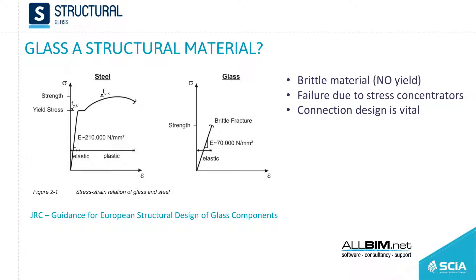Glass is quite a daring structural material because of its lack of redundancy. Glass is an elastic material, and when we compare it with steel or timber, those materials have the possibility of yielding. We can have plastic deformations and redistribution of tension, so if we under-evaluate the loads, distribution in plastic domains can ensure some redundancy to the structure.